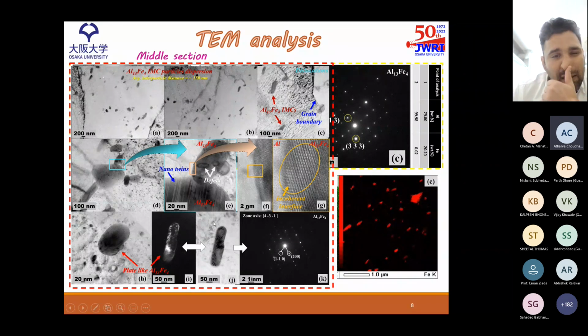Another feature is that this is the IMC particle and it shows some nano twins. Now, what are nano twins? These are the defect structures in the IMC particle. And what happens is that when the dislocation tries to move across this particle, these nano twins provide a blockade, and due to this blockade, the dislocation is forced to have a bowing motion instead of shearing motion. So the particles cannot be sheared easily, and that's why they provide precipitation strengthening.